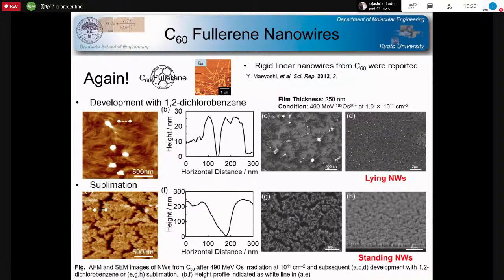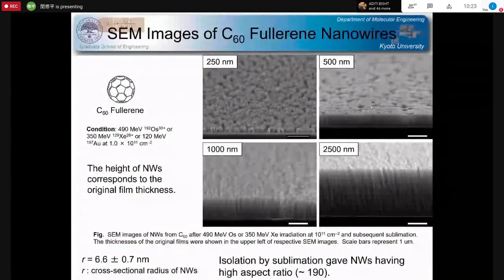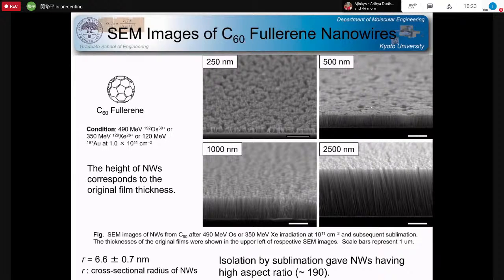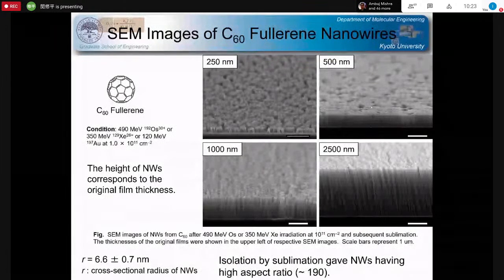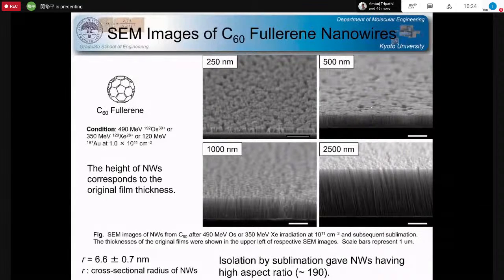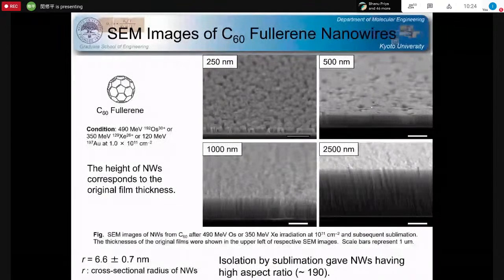However, to remove the unreacted part, we don't have to use organic solvents. For instance, in this case, Buckminsterfullerene has a very low but certain vapor pressure. So by the sublimation process of the unreacted part of the molecules, we can remove it very efficiently in a completely dry process to isolate the one-dimensional organic nanowires. As seen in this viewgraph, completely straightforward standing nanowires were realized by the sublimation removal of the unreacted part. And such very clean standing nanowires also extend their feasibility to wider application areas, for instance, more highly efficient sensing platforms, medical applications, or energy converting systems.